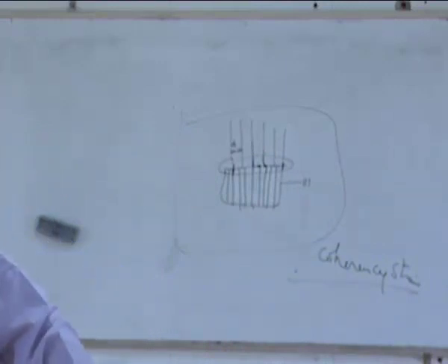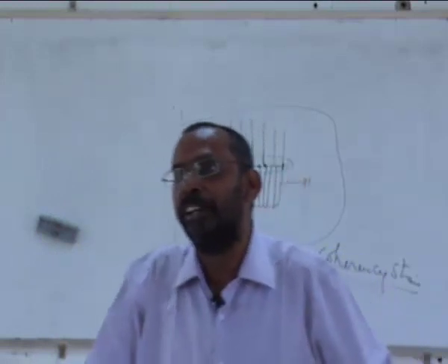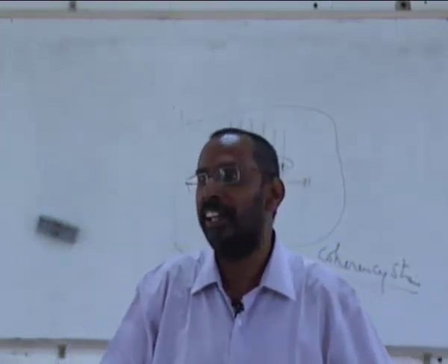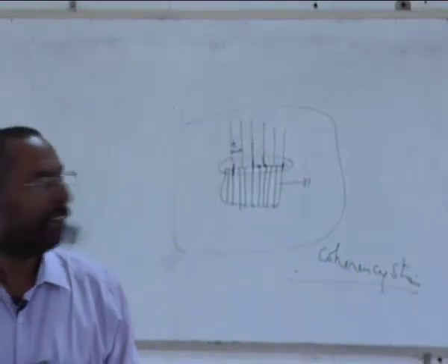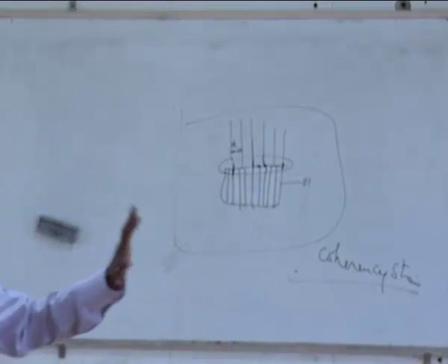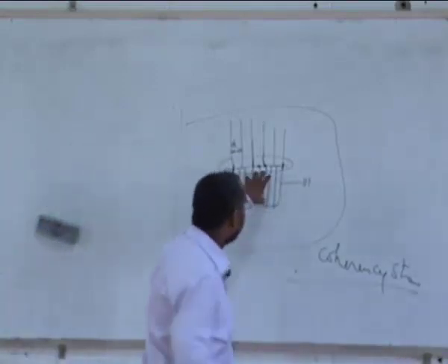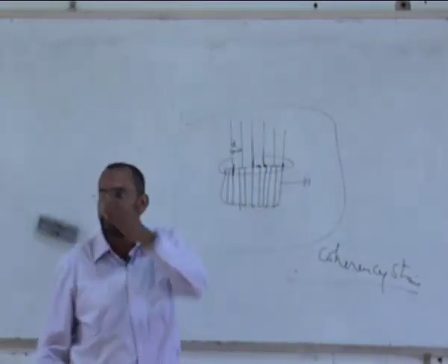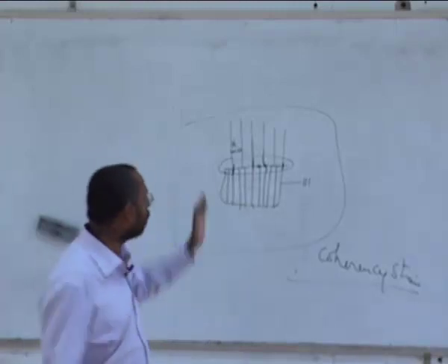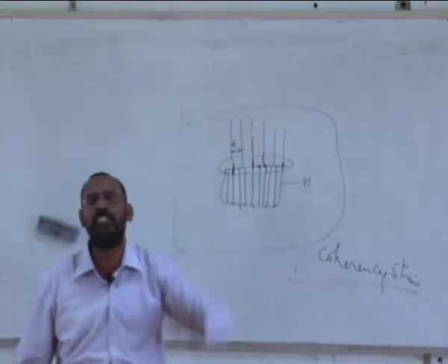If you want to know why that is so, I want you to go back and read a book such as Callister, or Material Science by Raghavan. You will see clearly that the packing can be seen, or go to Google, you will be able to see this. I don't want to spend too much time on that, but I wanted to say that yes, if I have an HCP particle and an FCC matrix, I can still have a matching, because that particular 0001 plane of the particle and 111 plane of the matrix can have a matching.